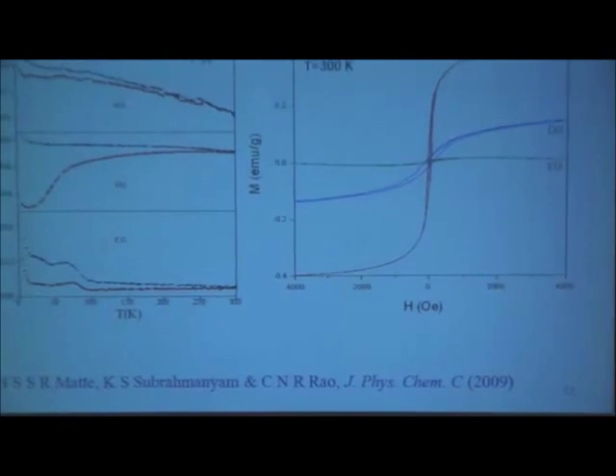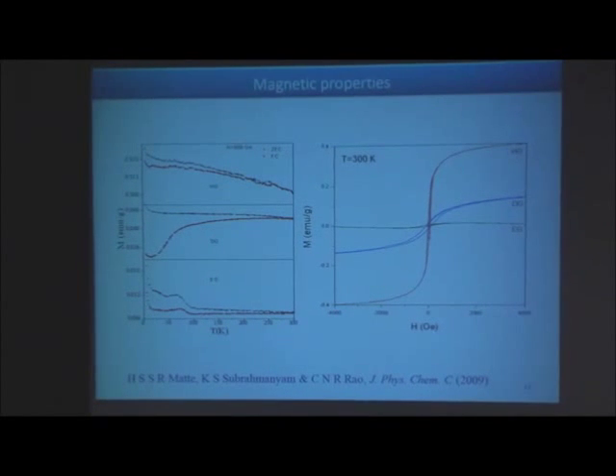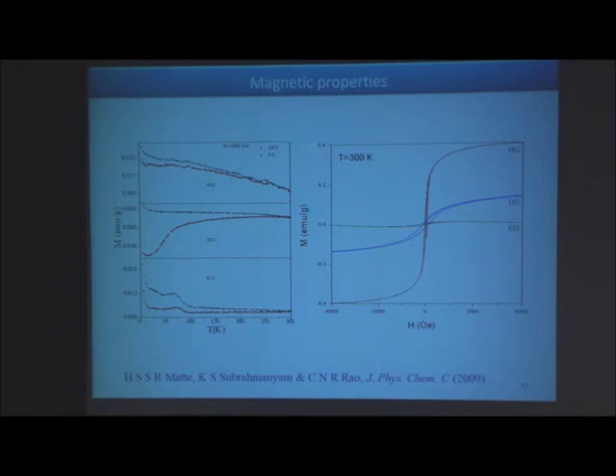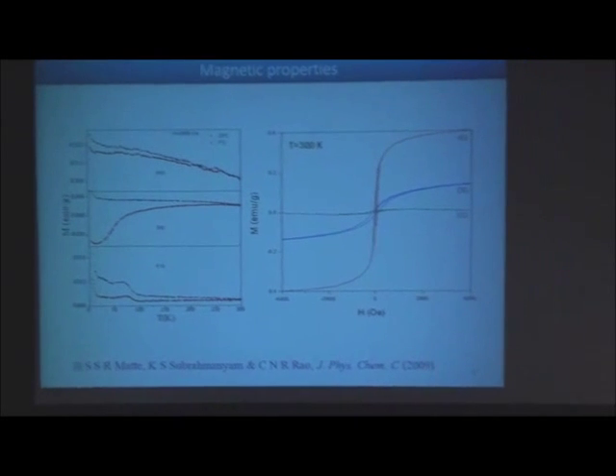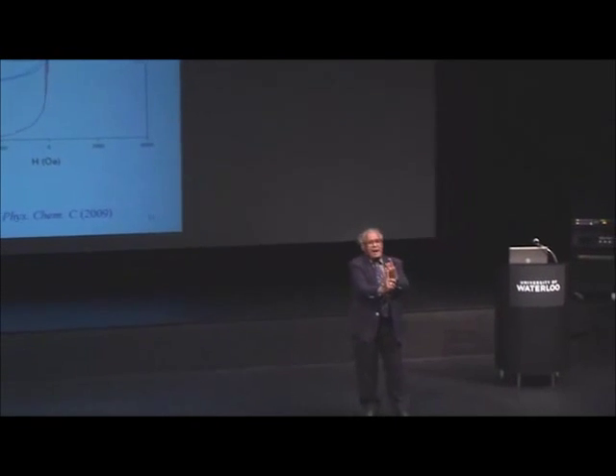Well, this is something I'm not going to discuss too much. I wanted to know, no matter how I make graphene, how much trouble I take to purify it, whatever you do, I cannot avoid getting magnetic hysteresis. There's no doubt all graphene samples are weakly ferromagnetic, weak magnetism. Why does it come? It is because of the lone pair orbitals all around the graphene. In the middle you have got the carbon sheet, the 6-membered rings, that will be antiferromagnetically coupled. So you have an antiferromagnetic background surrounded by these ferromagnetic lone pair orbitals. And in fact, now there are 3 theory papers which refer to our experiments as well, who show why it should be ferromagnetic, etc. So there's a lot of theory on that as well. But anyway, they're all weakly ferromagnetic in terms of magnetic hysteresis.